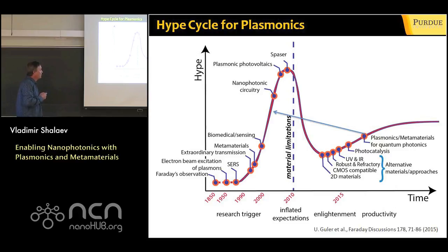We could argue that plasmonics started in 1857, with the first demonstration by Michael Faraday of how to reproducibly make these nanoscale plasmonic particles. Of course, they were not even called plasmonic at that time. It was just gold and silver. He used this reduction reaction between two salts. And if you go to a museum in London, you could still see the setup which Michael Faraday used to make these colloidal particles of gold and silver by doing this reduction reaction. And the funny thing, we're still doing it the same way when you do it chemically, this gold and silver